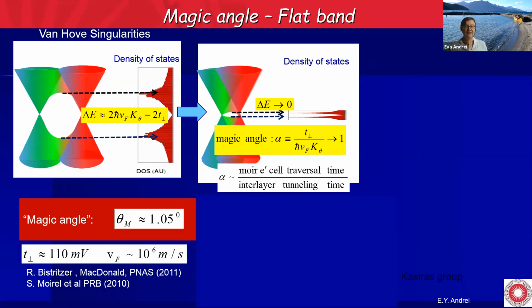Now, this magic angle, for standard parameters of interlayer hopping taken from bilayer graphene and standard Fermi velocity, is about 1 degree. However, this number is not carved in stone because, for example, we can change the interlayer hopping by changing the distance between the layers. This was already demonstrated by the Columbia group, that when you apply pressure, you change this magic angle. And also you can change VF by, for example, screening.